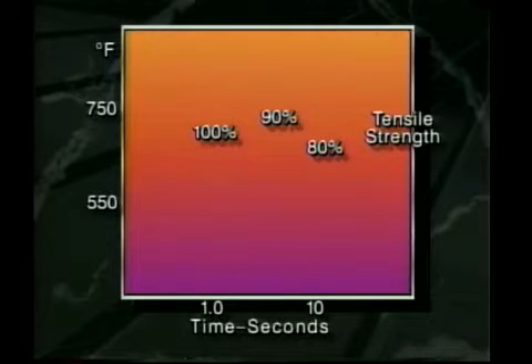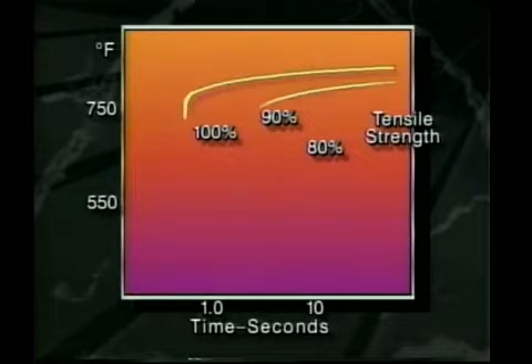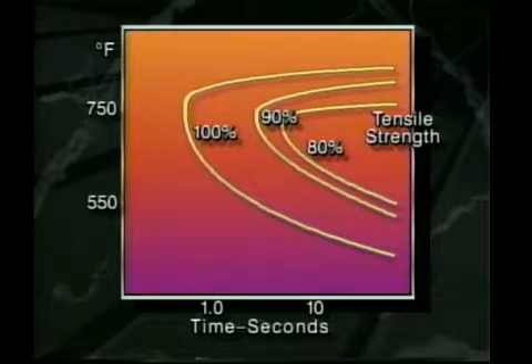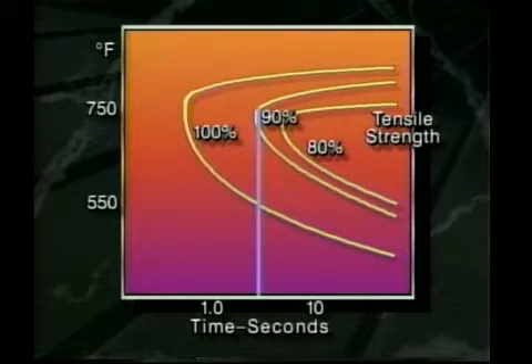The first question is answered by the C curve in this illustration, which shows the property loss that occurs when an aluminum alloy is held at different temperatures during the cooling process. It shows that the temperature range of 750 to 550 degrees is most critical. When held at a temperature of 675 degrees, the high-strength alloys begin to lose properties in a very short time, less than 1 second. When the part was held for only 7 seconds at 675 degrees, the material lost 10% of the strength that would have been achieved by quenching directly.